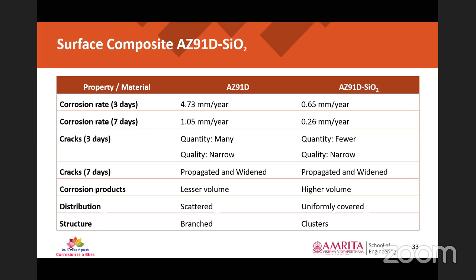Added to that, the cracks have propagated and widened relatively in both the specimens, whether base material or composite. The corrosion products have lesser volume in AZ91D, but the corrosion products were more in the case of the AZ91D silica based composite. The distribution of the corrosion products is scattered in the case of base material AZ91D, but in the case of the composite, it is uniformly covered. Added to that, the structure of the corrosion product has changed from the base material towards the composite too. In the case of the composite, we had clusters of corrosion products.